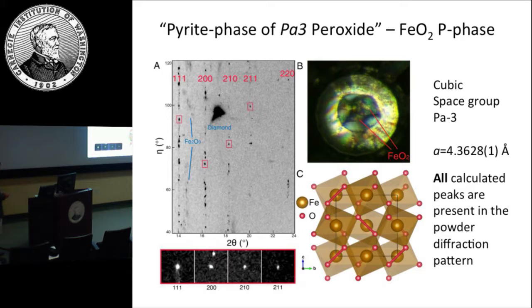The sample, after the heating, became partially translucent. Before, it was dark. The hematite was dark before, and then after heating it became translucent. The diffraction is very spotty, which is good for us to really identify the structure. With a powder pattern, even if you have 10 lines agreeing, it can still be fortuitous that some structure has lines that agree. But if it's a single crystal, each crystal has its orientation, then you can check the orientation matrix and check all the spots. Then there's no doubt what it is.